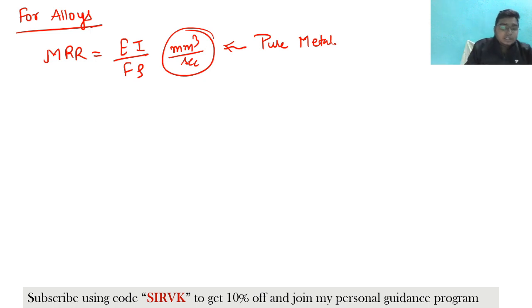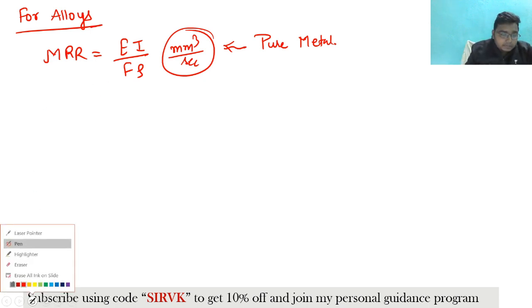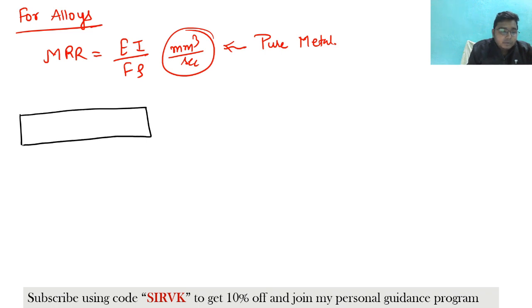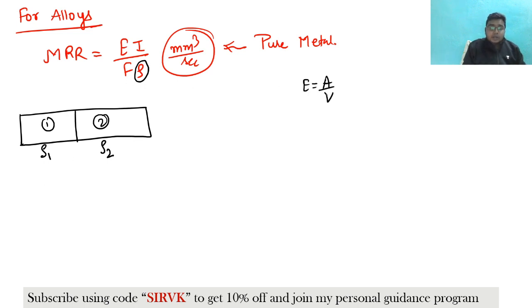Now what is happening for the alloys? If the material is made of two materials, suppose material 1 and material 2, they will have different densities, density 1 and density 2, isn't it? If the materials are different, the densities will also be different. So my density is not constant. Clear? Now also, what is this E? E is A by V. If my material is different, definitely the valency and the atomic weight will be different, and suppose it is A percent and B percent, then percentage wise the composition is also changing. So it is very complicated, figures are getting out.